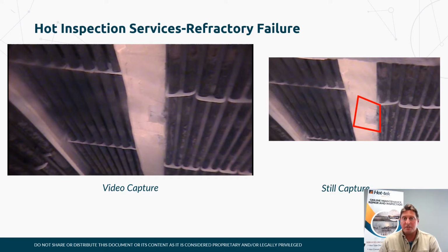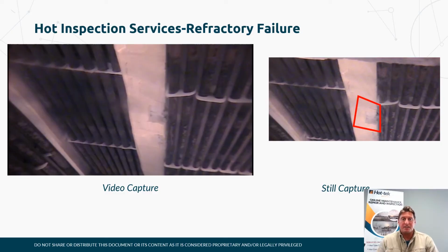So here we will actually see, this is about 35 or 40 feet away, so it wasn't a very polluted area, so we were able to just stabilize the lance at the bottom, and then zoom in up to the ceiling where we were addressing. We found an external hotspot. We weren't really sure of the extent of the failure, so we were able to put the lance in at the 90-degree angle and zoom up to see the damaged area. And then again, on the right side, we can see the still image that we were able to pull from that video.